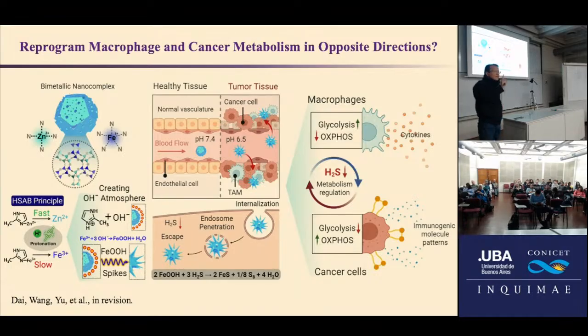However, we have identified one intrinsic molecule for this immune modulation, which is hydrogen sulfide. We could use hydrogen sulfide downregulation to promote glycolysis upregulation in the macrophage and glycolysis downregulation in the cancer cell. To achieve this, it is also based on a spiky nanoparticle, which I'm quite familiar with. So we use a bimetallic MOF, which is zinc and iron. And under mild acidic conditions, this